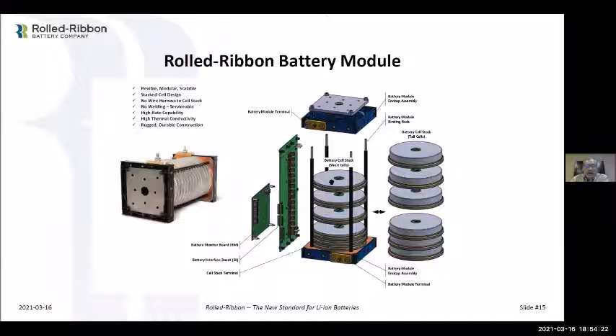The difference between, well, I'll show you that later, but basically the difference in thermal resistance between going layer to layer in anything that's wound or stacked versus the edge of the foil in contact with the cell can surface is on the order of, at minimum 20, and it's usually on the order of 100 to 200 times lower. So we have completely unmatched, low thermal resistance.